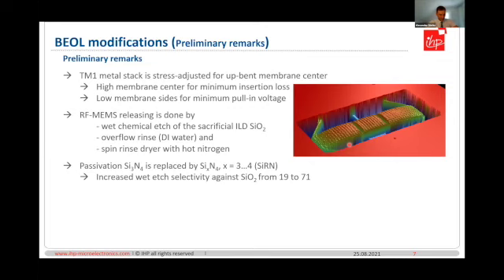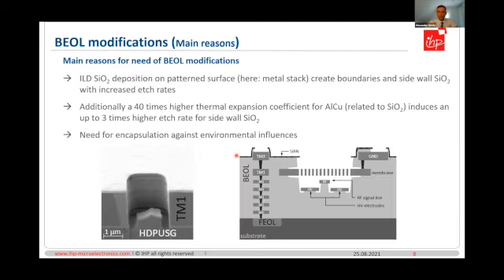Furthermore, the RF-MEMS releasing is done by a wet chemical etch of the sacrificial ILD silicon oxide, together with an overflow rinse and spin rinse dryer with hot nitrogen. Finally, the passivation nitride is replaced by silicon-rich nitride in order to increase the wet etch selectivity against silicon oxide from 19 to 71.